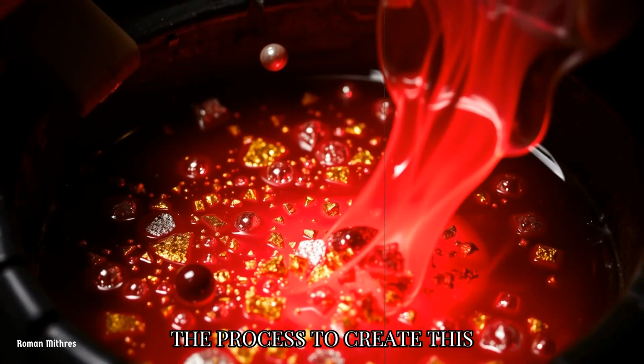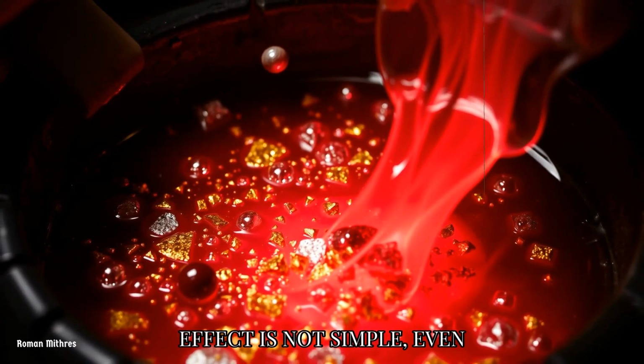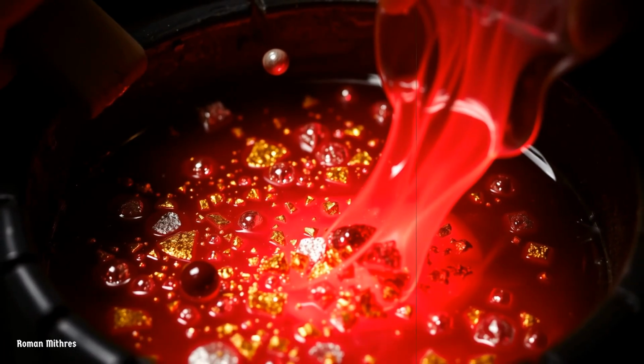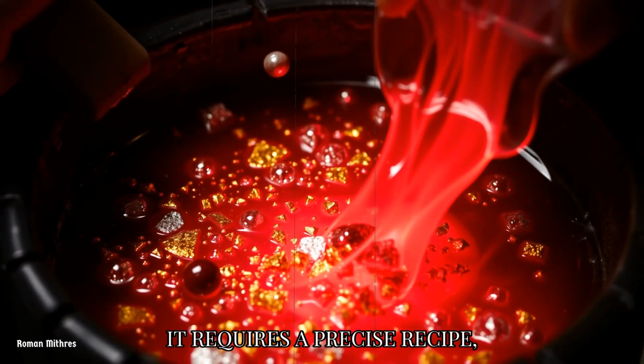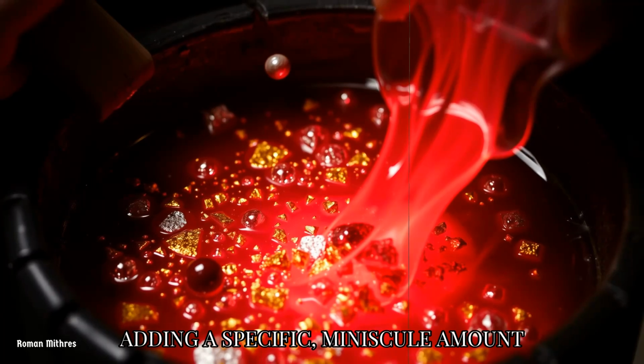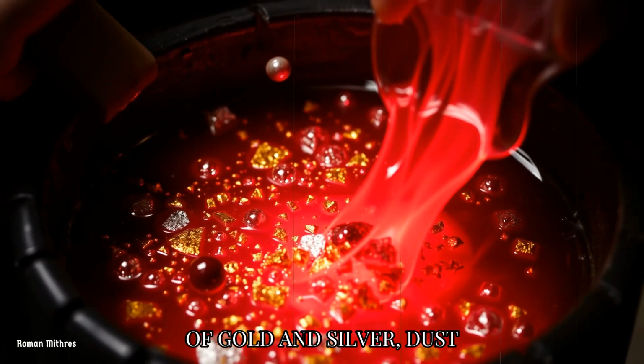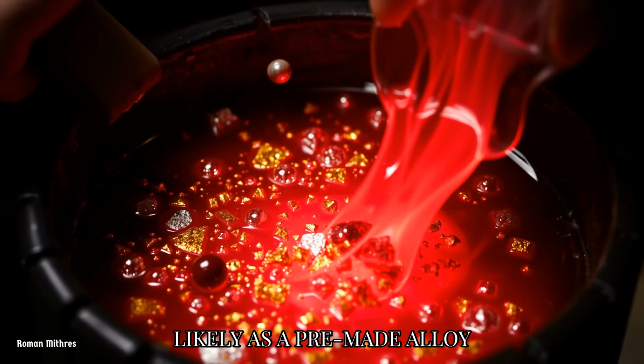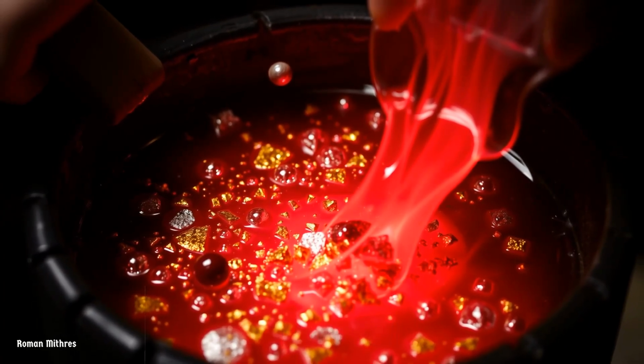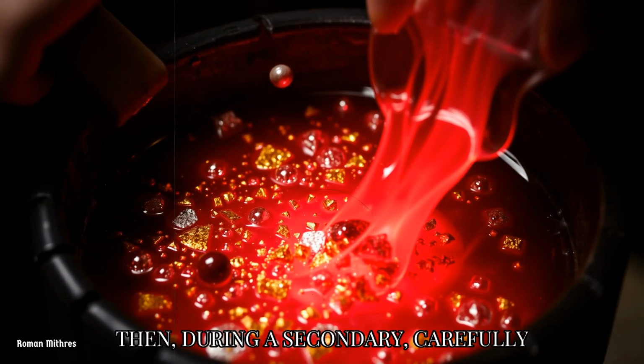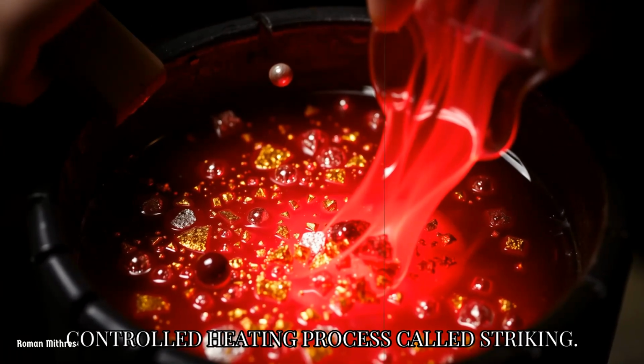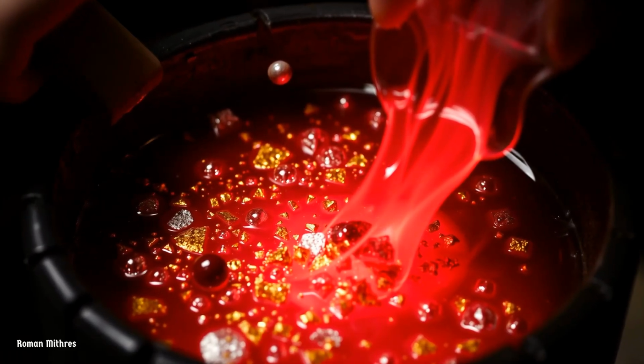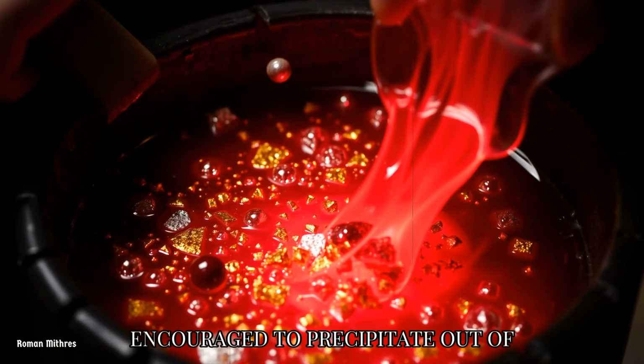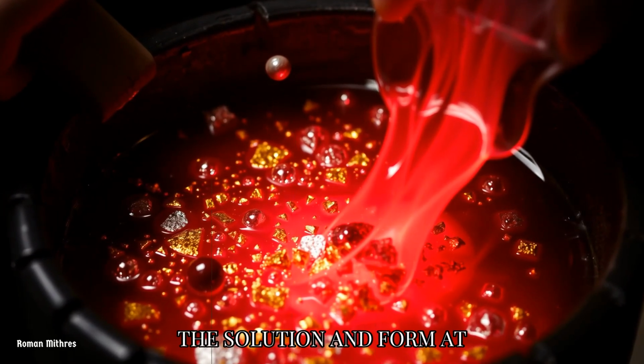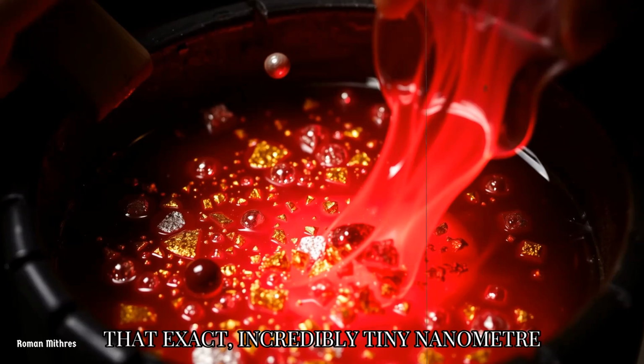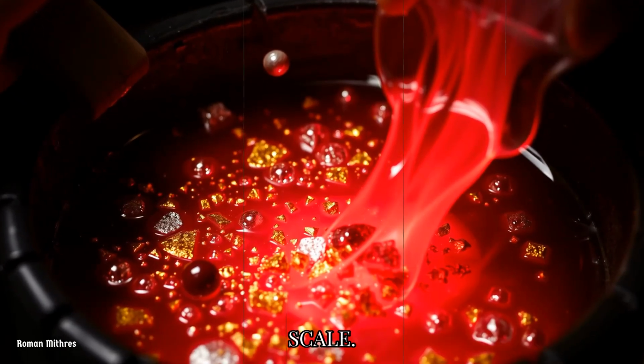The process to create this effect is not simple. Even with our modern understanding, it requires a precise recipe, adding a specific, minuscule amount of gold and silver dust, likely as a pre-made alloy, to the glass batch. Then, during a secondary, carefully controlled heating process called striking, those metal particles must be encouraged to precipitate out of the solution and form at that exact, incredibly tiny nanometer scale.